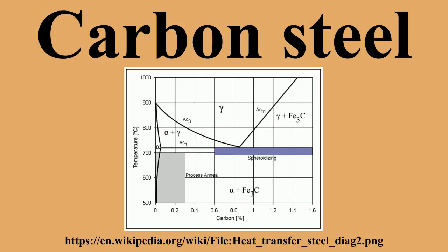The following is a list of the types of heat treatments possible. Spheroidizing. Spheroidite forms when carbon steel is heated to approximately 700 degrees Celsius for over 30 hours. Spheroidite can form at lower temperatures, but the time needed drastically increases, as this is a diffusion-controlled process.